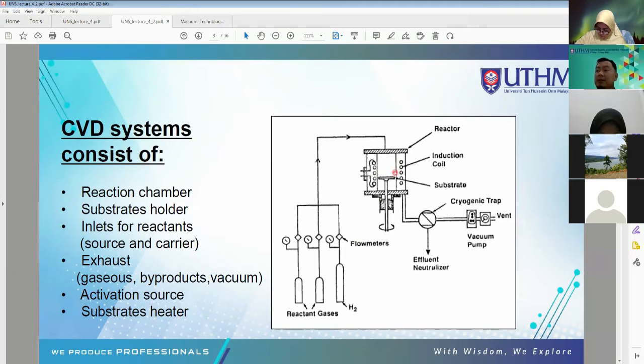We have the induction coil inside here. You can see it circles around the chamber, and then we supply the power, for example AC voltage, to heat the chamber. Then we get the energy. That energy will make the reactant gas reactive, and then it will deposit on the substrate, because most of the time the substrate is cooler compared to the environment, so it will deposit on the cooler side. That is the reaction. To make sure the chamber is a vacuum, we have the vacuum pumping system like here. Then we can have a good process here.